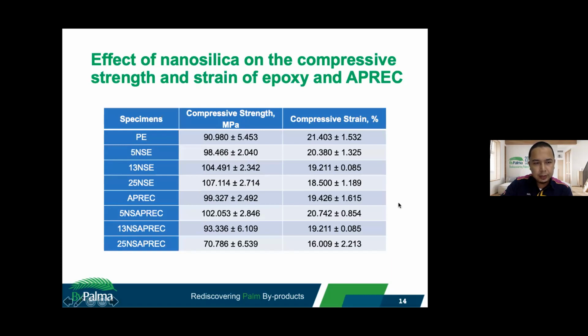And then this is the result of the effect of the nanosilica on the compressive strength and strain of epoxy and APREC. As you can see, the addition of 5, 13, and 25% of nanosilica into the epoxy increased the compressive strength of the epoxy, and then the addition of 5% of nanosilica into the APREC improved the value of compressive strength of APREC. However, the value dropped if we add 13 and 25% of nanosilica.